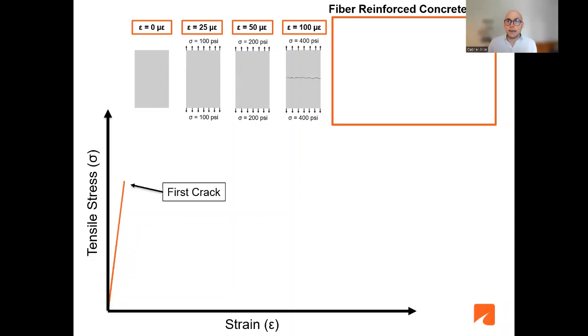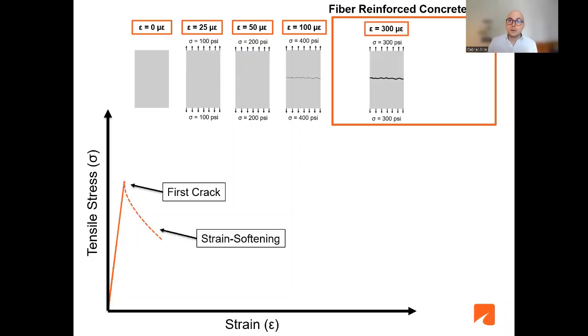Next, let's see what happens when we have fiber reinforced concrete. If we have a conventional fiber reinforced concrete, after this first crack you're going to have a strain softening behavior, meaning that after that first crack, you have a residual load carrying capacity. Nonetheless, this capacity is lower than the original concrete material prior to cracking. And if you continue deforming these materials, the load will continue to go down, and that crack will continue to open until finally you have a complete rupture of the material, a complete failure. So it's important to notice that, similar to conventional concrete, this fiber reinforced concrete, after the first crack, is already in a failure regime, right?